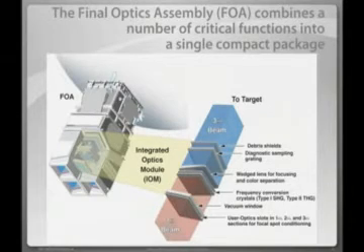And we have developed techniques in not only bulk materials, but finishing techniques, cleanliness techniques, coating techniques that are becoming, hopefully, more and more a part of the industry that we are here for today. And we have other ideas that hopefully will double or triple that, and we'll be publishing that in the months ahead. That will bring us hopefully to the 20 joule, 30 joule per square centimeter damage points for short pulses.